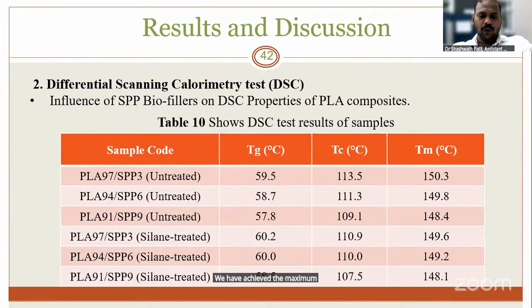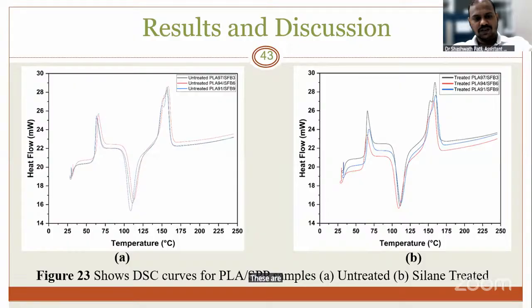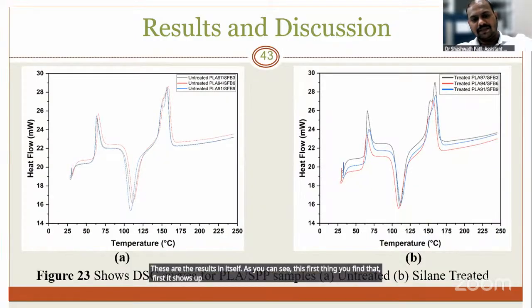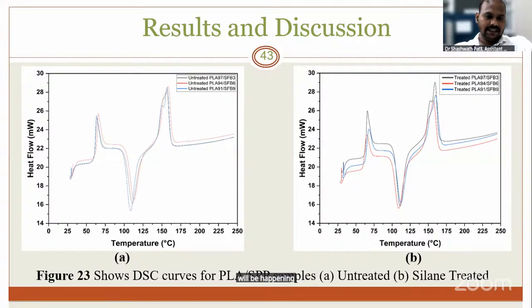This is the differential scanning calorimeter. As you can see, Tg is the glass transition temperature, Tc is the crystallization temperature, and Tm is the melting temperature of the sample. We have achieved a maximum of 60.2 for the 3% silane treatment, a crystallization temperature of 110 degrees, and a maximum melting temperature of 149. As you can see, the first peak shows the glass transition temperature, and the second lower peak shows the crystalline stage, where the cooling stage happens. Then again in the melting stage, it shows a peak of 149.6.